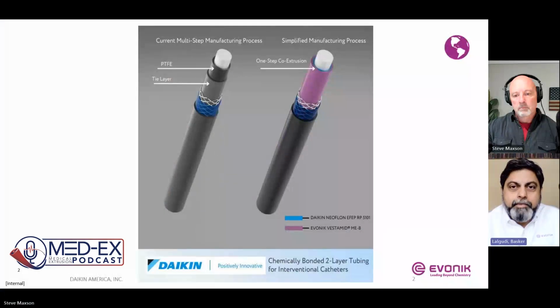Yeah, absolutely. So, Steve, historically, if you look at the construction of the catheters, multi-layer catheters, whether it's PTCA angioplasty or guide wire catheters, you have fluoropolymers on the inside for lubricity, and then you have VESTAMID PEBAs on the outside for flexibility and kink resistance. Now, because those two chemistries are very dissimilar, they're not compatible to each other. The process that's been used in the last 15 to 20 years involves multiple steps, 6 to 7 steps actually. There is chemical etching involved, there is mechanical etching involved, there's usage of expensive adhesives, and it's time consuming. It requires a lot of resources, and it costs energy. There is energy cost there too.